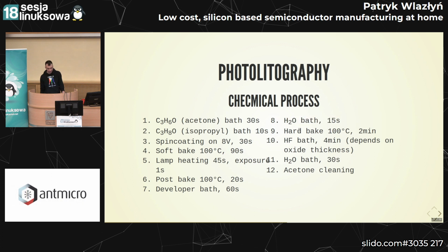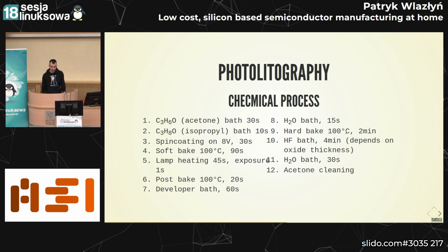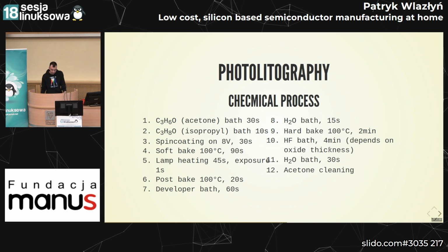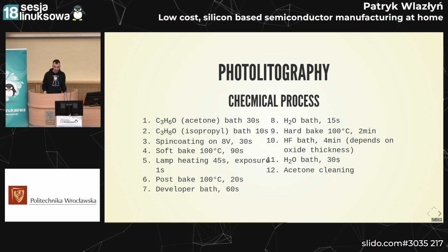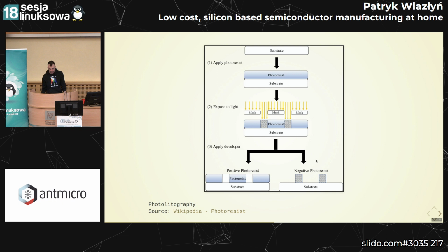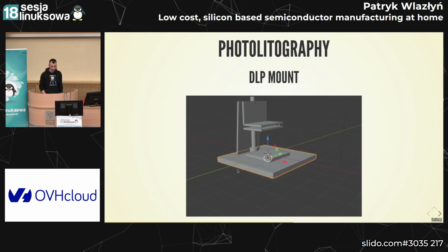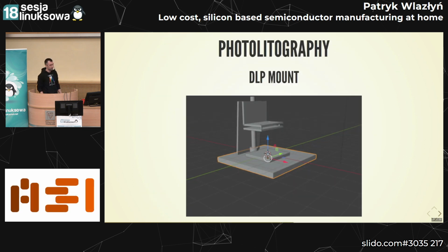Then we clean with H2O, and again, vapor out basically any H2O that was left on the wafer. And then we do an HF bath for 4 minutes. It actually depends on the thickness. If the thickness is bigger, we will have to do more. And then we clean the wafer in H2O and basically do an acetone cleaning at the end. And we would have this kind of wafer at this stage that has the washed away photoresist, and the HF will remove all the dioxide that I was showing on, I think, the second slide or something like this.